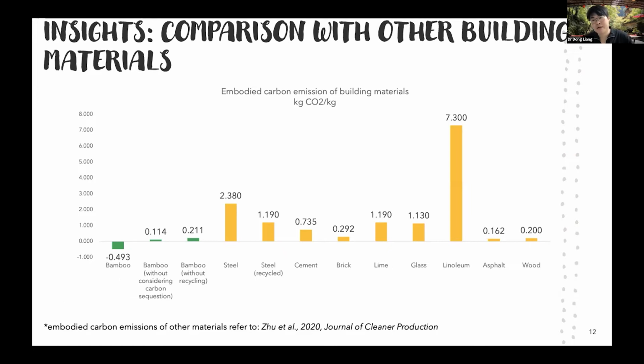And we further compare the bamboo carbon emission with other materials in buildings. For example, the number we can see here is still very high and intensive, and of course the high carbon emission is about 2.38 kilogram CO2 emission per kilogram of steel. And if we look into some other material that could potentially be substituted by bamboo, we can see wood is about 0.2 kilogram CO2 emission per kilogram of wood. So it's very close to bamboo without recycling.